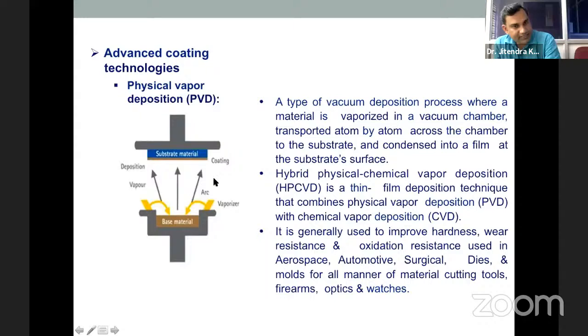Physical vapor deposition is nothing but this: here is the crucible, and this whole thing you can perform in a vacuum chamber. In that vacuum chamber you have the heating filament, and you keep the material, say gold, to coat over the substrate. On top you keep your substrate, and here you keep 1 milligram of gold, or maybe less than that, or silver, whatever the material. That material melts, and after melting it evaporates. At the time of evaporation, the substrate on top accumulates those evaporated particles and the coating is generated.